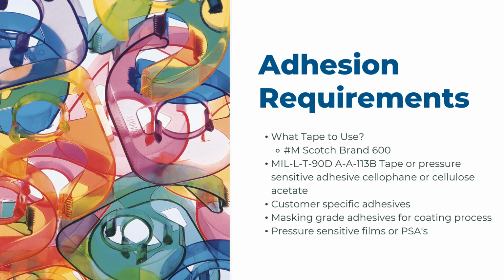and there could be some interaction of the chemistry with the pressure sensitive film and the last layer of your coating film. So when specifying that there should be some protection on the surface and when specifying a pressure sensitive adhesive to be used, chemistry really has to be considered. And that's just kind of a pitfall that through experience we know, and understanding how to use pressure sensitive films, that also can help as you specify how to package, how to ship your optics.